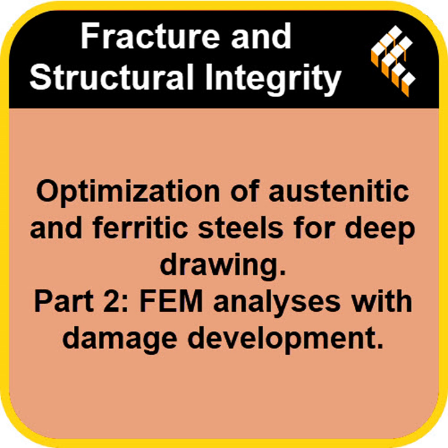And you mentioned the stress levels were different too. Yeah, this was fascinating. In this low-friction stretching failure mode, the von Mises stresses actually reached over 1,200 MPa at the apex before failure occurred. So higher than the 1,000 MPa peak seen in the drawing failure mode. Considerably higher, suggesting that with good lubrication, you're actually able to utilize more of the material's inherent strength before it fails. That ties into the thickness measurements too, right? The FEM simulations showed how the thinning happened over time. Yes, that gave real insight. Without lubrication, once the initial cup shape forms, the thinning effectively stops under the punch nose.